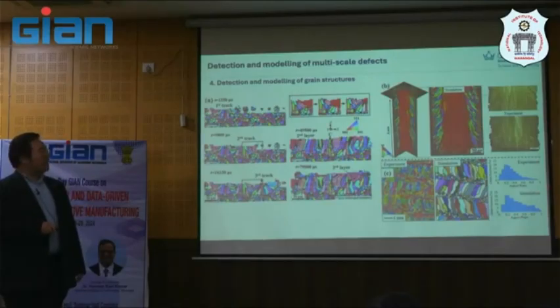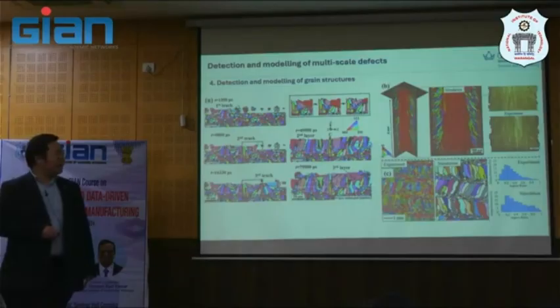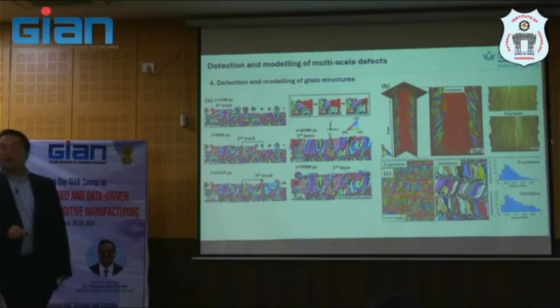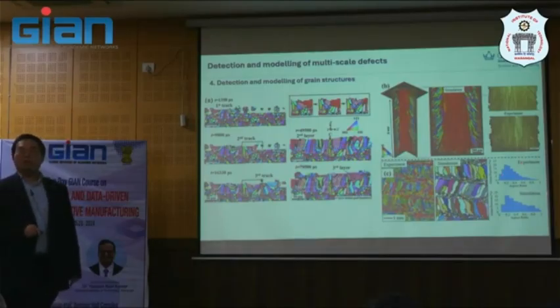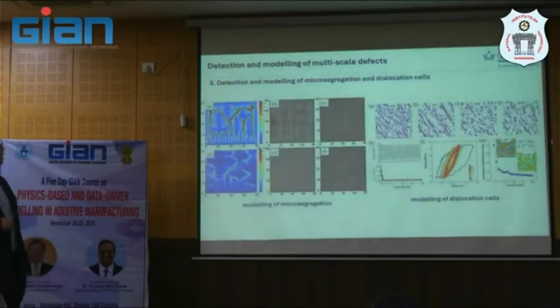One means near equiaxed, sorry, near equiaxed, yes, that's correct. If you go to 0, it's more columnar. So this one is a left distribution here. This is more columnar grain, which is the same as you observe experimentally here. So simulation and experiment probably tell similar things. It's quite good agreement that they can predict the distribution or statistics of the microstructure here.